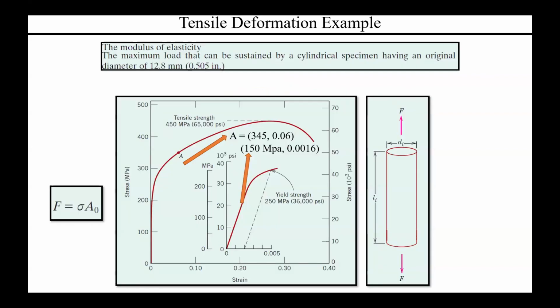So we're going to do another example here. There are two questions that you need to solve. The first is the modulus of elasticity: given all this information, figure out what the tensile modulus is. And the second is the maximum load that this cylindrical rod can sustain if you have an initial diameter of 12.8. Note that the 150 MPa, 0.0016 is pointing to a point within the linear region of the subplot, and the subplot is just a zoomed in region of the very beginning of the much larger plot. Again, that A point there, A 345, 0.06, is literally pointing to the A on the plot.